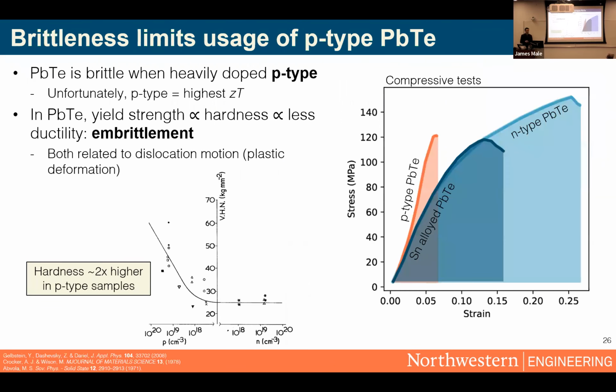Now, these are very understudied in thermoelectric materials. So the mechanical properties in these systems are at quite early stages at this point. But one thing we have found is that lead telluride seems to be very brittle in certain configurations. This is something that people have found qualitatively. If anyone has ever made lead telluride, they know if it's P-type, it's super brittle. If it's N-type, it's actually pretty robust.